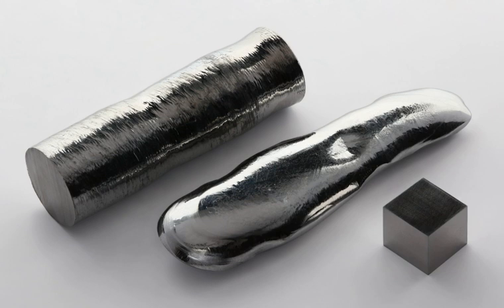Rhenium is also used in the superalloys, such as CMSX-4 second generation and CMSX-10 third generation, that are used in industrial gas turbine engines like the GE 7FA. Rhenium can cause superalloys to become microstructurally unstable, forming undesirable TCP, topologically close-packed, phases. In fourth and fifth generation superalloys, ruthenium is used to avoid this effect. Among others, the new superalloys are EPM-102 with 3% Ru and TMS-162 with 6% Ru, as well as TMS-138 and